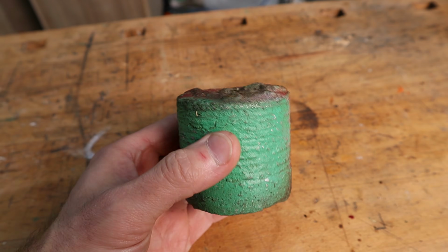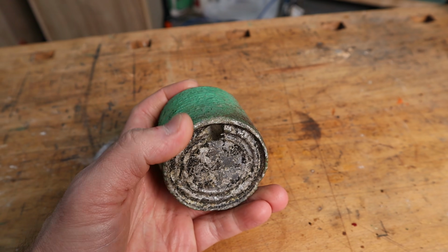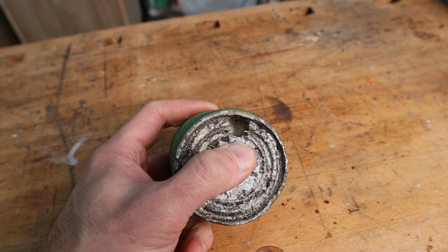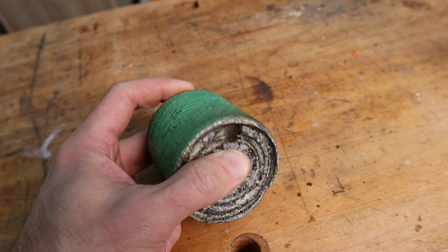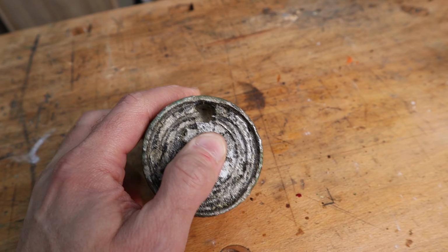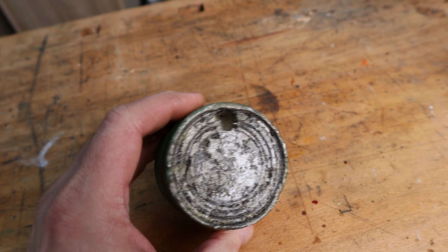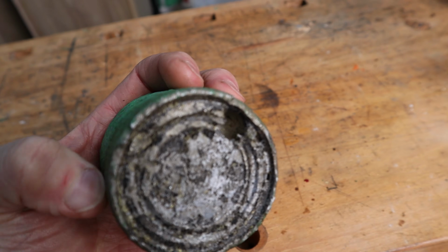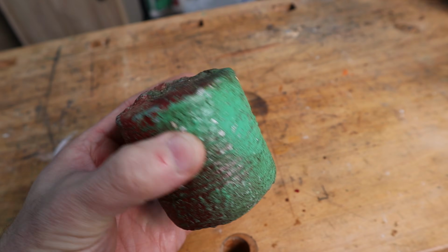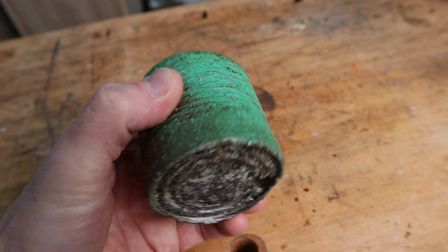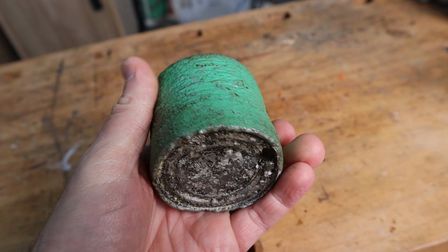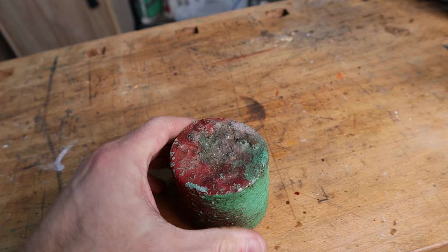This is what it looks like if we were to cast directly into a metal tin. Those tins do tend to be lined with some type of plastic. So the hot molten metal goes in. Sometimes these gas bubbles can form and they can't get out. So we have these big voids, unfortunately. On the top it's quite rough, so that's not really great. And we don't have any hole in the center either.